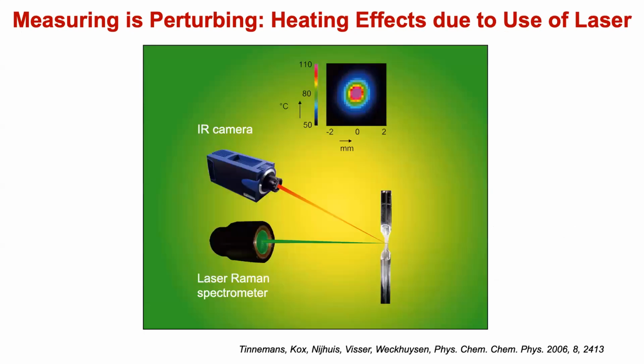Now we have been doing something with an infrared camera. You can use an infrared camera to follow the heat. You agree? So with an infrared camera we have been measuring the heat, and on the top you see the increase when the laser is on or off. Of course, this is a certain experiment that has to do with the flow rate and whatever, so it's not so important what the value is. I only show that with an infrared detector, you can actually measure the heat increase. It's there.